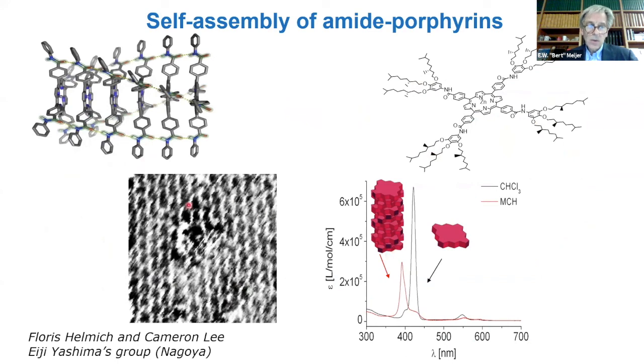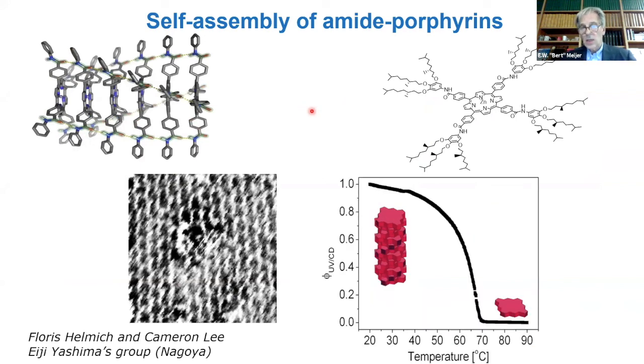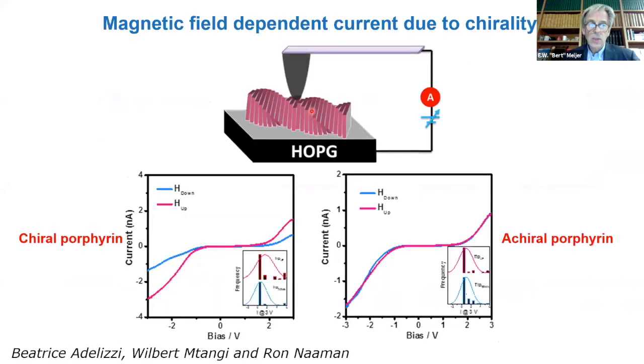We did it together with Yashima's group in Nagoya, microscopy. You see the helix here, and this is a kind of cartoon of what we think it is. We look at how we can make the polymer forms. That goes by nucleation-elongation growth, so we have everything under control. Then with these chiral structures, as well as with the achiral structures, we went to Israel to measure together with Ron Naaman IV curves on these chiral aggregates and on the achiral porphyrins.